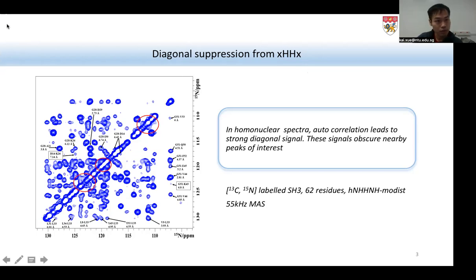So as you see here on the left side of the spectra that is obtained, that is a homonuclear spectrum. We normally observe these autocorrelation peaks. And these autocorrelation peaks are normally a few times more intense than the structurally important mixing peaks, the cross peaks. And these strong autocorrelation signals sometimes obscure the nearby peaks of interest.